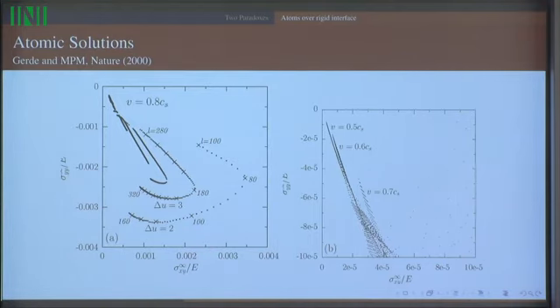Because the back end is actually, if it's 100 long, then the back end is plopping down at atom 97, hence creating a little pucker and allowing a little bit of slip at the end of the day. So this solution with delta U equal to 3 results in a net slip of the upper solid of 3, and the slip pulse here, for example, is 180 atoms long. So those are these little running bubbles that we claim analytically exist.